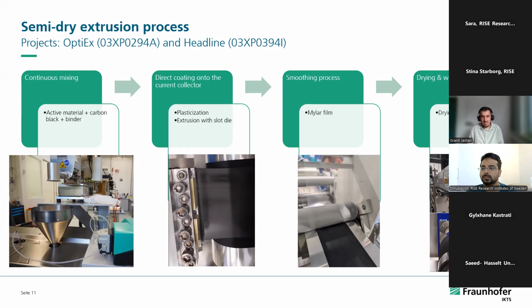Then in the second step, you can see how the direct coating onto the current collector is done. You can see that the film is well homogenized and plastified in order to have good adhesion to the current collector. In this process, at the moment, we are using mylar film, which is necessary due to the smoothing process.